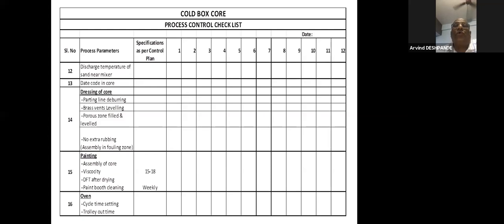Date code on core, because after 48 hours or 78 hours the strength drops, as core sand is hygroscopic in monsoon. So that has to be checked and we can correlate the rejection also. That's why date code on core. Then dressing of core: parting line deburring, brass vents, leveling, porous zone filled or not. Of course, this checklist is related to manual operation, not robot, so accordingly I have designed this checklist. Porous zone filled, no extra rubbing.